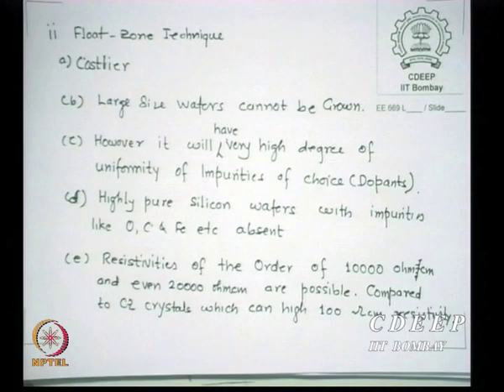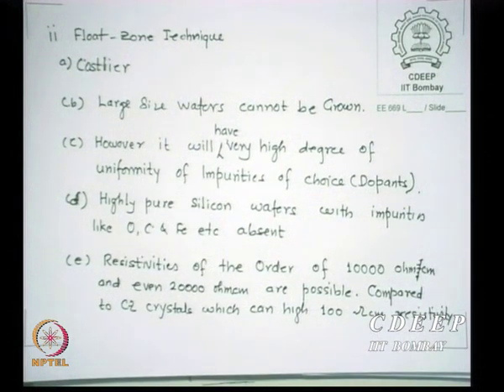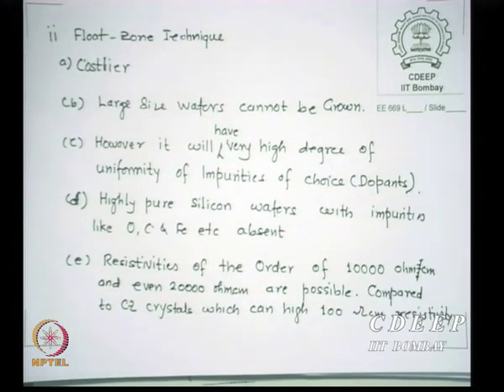So why are we looking at Float Zone? Float Zone is also important, but for float zone you need a CZ crystal initially. So you can say it is an added process — it is significantly more costly comparatively. It is impossible to grow large wafers using this technique. However, it has the feature that it provides a very high degree of uniformity of impurities across the wafer and along the rod.